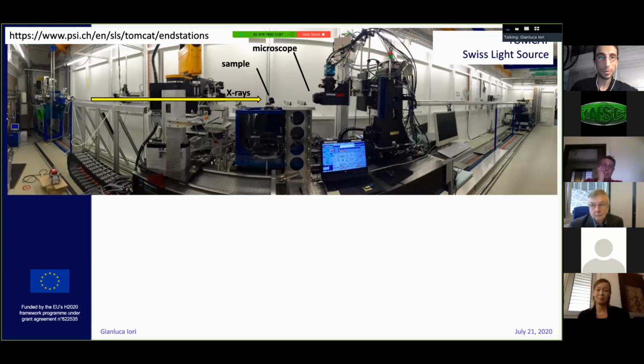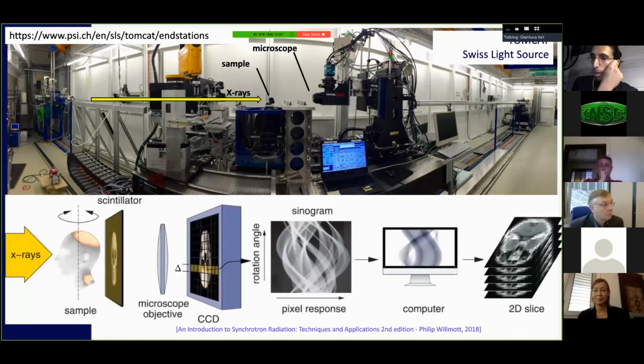How microtomography at a synchrotron laboratory looks is actually very different. This is a picture from TOMCAT, a micro CT beamline at the Swiss Light Source. The X-rays are entering from the left. This is the X-ray path. There is a sample manipulator in the middle, and on the right there is a microscope. And you see already the length of the experimental hatch, allowing us to modify the propagation distance between the source and the sample, as well as between the sample and the detector. So how this works is, very roughly, in this way.